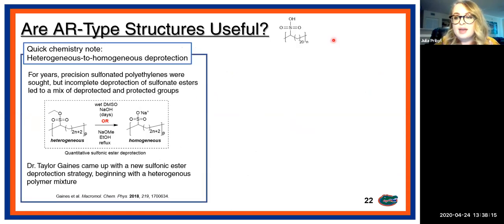So one thing that we desire to look at is precision sulfonated polyethylene. So this type of structure here. I want to point out right now, a quick chemistry note, because this looks like a simple structure, but in reality, this was not an easy polymer to prepare. For years, this type of precision sulfonated polyethylene was sought, but the problem really ended up in deprotection of sulfonate ester groups. So what would happen is you would get incomplete deprotection of the sulfonic esters, and then what you have now is an imprecise polymer, because the pendant groups are a mixture of the esters and the sulfonic acid. So that's no good for studying precision polymers.